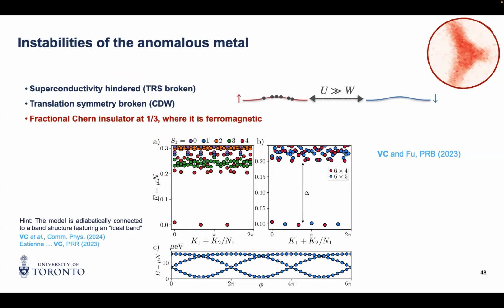And surprisingly, usually those things don't scale as well. It's a very small system size, about 30 sites that we can do. But the gap doesn't change as a function of 30 versus 24 sites. So it's more robust than the toy model from 2010 used to look at those systems. This is due to the band being so flat that it was extremely robust. So for us, it was really a surprise that it was that robust.